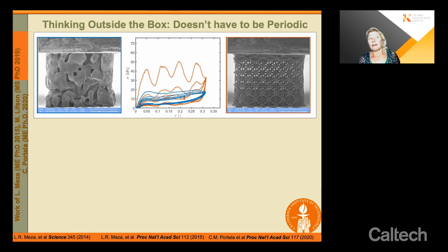It appears that the deformation of these materials is driven much more by the local distribution of stresses than by the globally applied stress. Even though it's complex in the sense that the stress landscape of the localized regions is very different between them, as long as it doesn't exceed the fracture strength, they will fully recover. And so that's what we're observing in the deformation of these hollow architectures. Now, these are made out of very brittle ceramics that typically are not known for strain rate effects. So this is alumina. Here there isn't much of a mechanism through which the strain rate would manifest itself. However, the metallic ones certainly would.